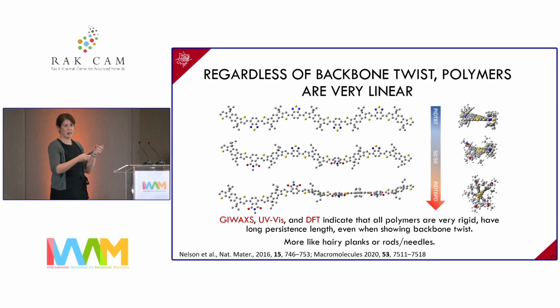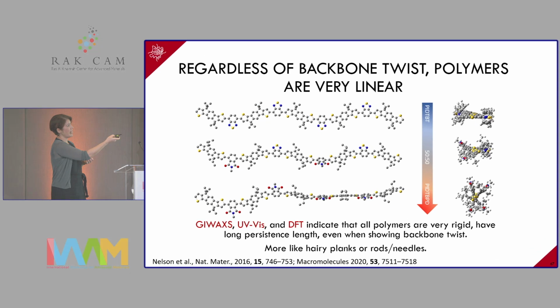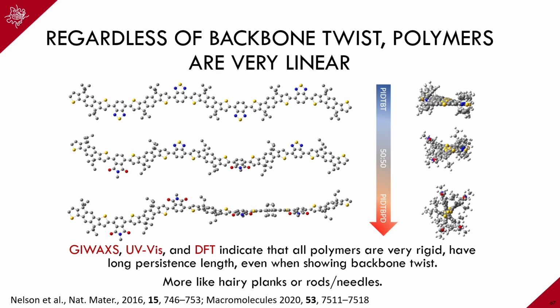So the core of it is still very linear, but what's changing is that because it's more twisted, the side chains are spiraling out. So you have 360-degree coverage of side chains along that rigid polymer backbone. But in the original IDT-BT, this one, this is more like a hairy plank. The polymer is planar, and then that means that the side chains just come off at the sides.